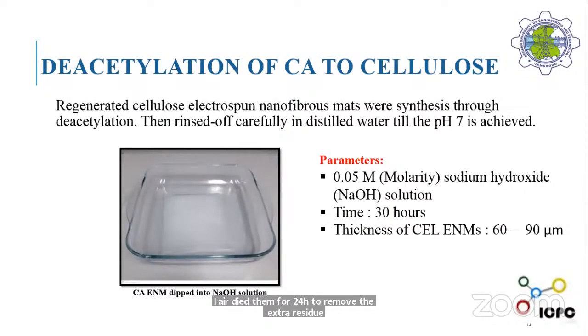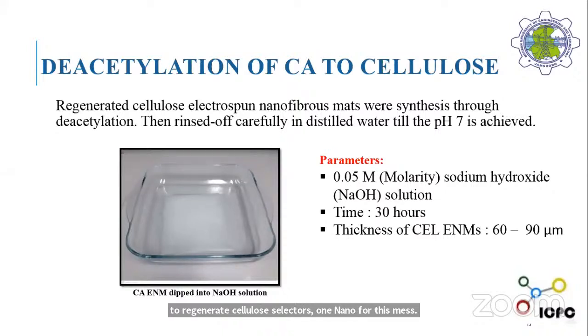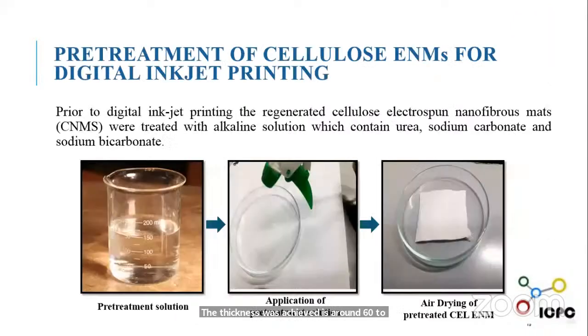After making cellulose acetate electrospun nanofibrous mats, to regenerate cellulose electrospun nanofibrous mats, we use a deacetylation process. For this, I dipped the cellulose acetate nanofibrous mat into 0.05 molar sodium hydroxide solution for 30 hours to get the regenerated cellulose electrospun nanofibrous mats by removing the acetyl group from the cellulose acetate mats. The thickness achieved is around 60 to 90 micrometers.